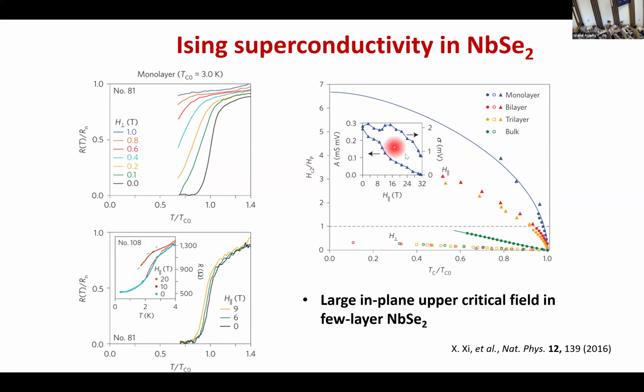So how do we understand this? When all the spins are locked out of plane and you apply an in-plane field, this in-plane field cannot rotate the spins. And also the in-plane field cannot induce vortices because the layer is very thin. So in this case, because of the spin locking effect, it's very hard to polarize the spin. So it's very hard to kill superconductivity. This is the idea behind Ising superconductivity.